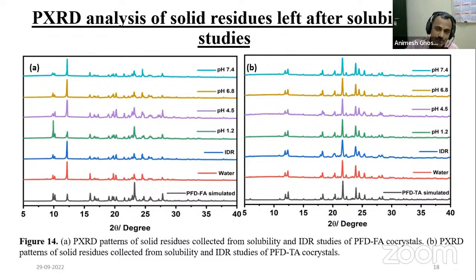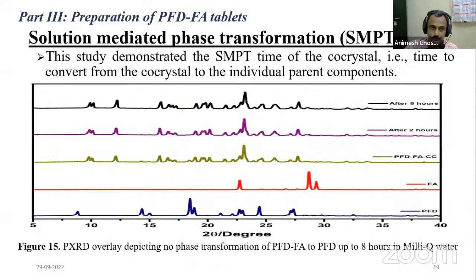So upon seeing the XRD data, what we have observed is that it is stable at all the pHs. That means the co-crystal is the saturated species in solution, and therefore the residue is also a co-crystal. It shows similar Bragg's diffraction as the co-crystal. So we can say its solution mediated phase transformation, or solution stability, is good. That is basically the solution mediated phase transformation study, which is most important from the formulation perspective.